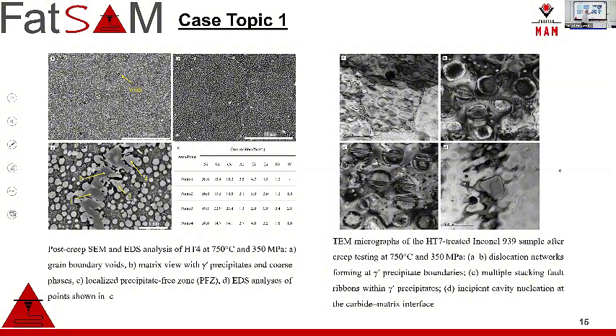And inside, they even cut through the gamma prime precipitate, some twinning in this microstructure. And due to rafting, we have gamma prime coarsening. As you can see, these are the small spherical ones as secondary gamma prime formations, which do not improve but postpone the fracture mechanisms during creep in these materials.